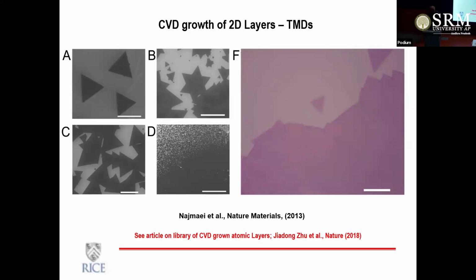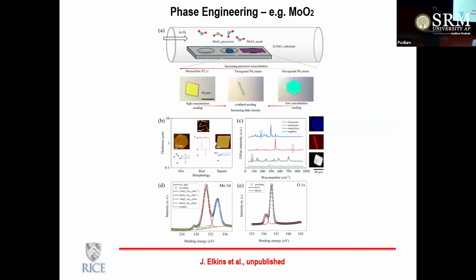So one of those candidates I'm going to pick up and talk about is the 2D materials: graphene, boron nitride, a very similar single atom thick material, or transition metal dichalcogenides, TMDs. These are interesting semiconductor materials which can also be peeled off like graphene, and you can actually make these single unit thick materials over a large area. So the last 20 years have seen an incredible amount of work in trying to controllably make these materials like TMDs, the transition metal dichalcogenides. These are typically materials like molybdenum disulfide or tungsten disulfide. They are again van der Waals, which means that they have these strong layers that are stacked together with weak forces so that you can easily peel off, or you can actually grow these single unit thick materials. We were, in fact, one of the early groups that started to pioneer this vapor phase growth of these types of materials in the early 2010s.